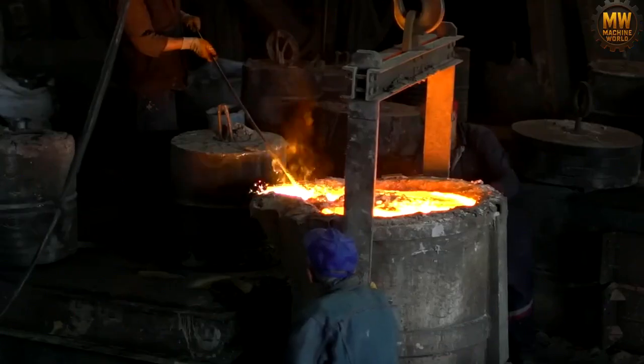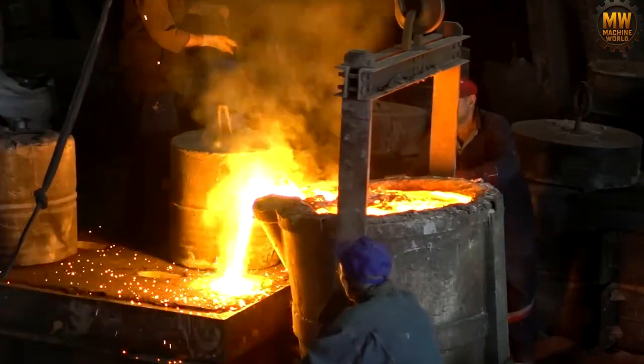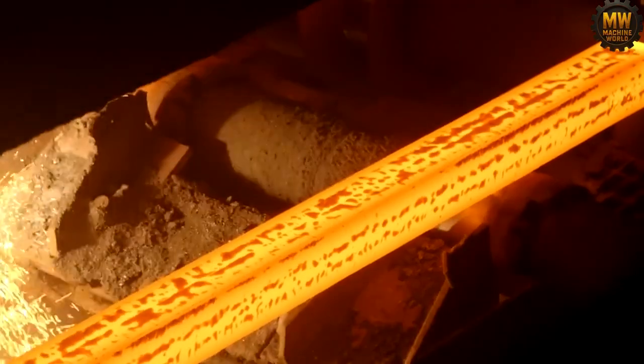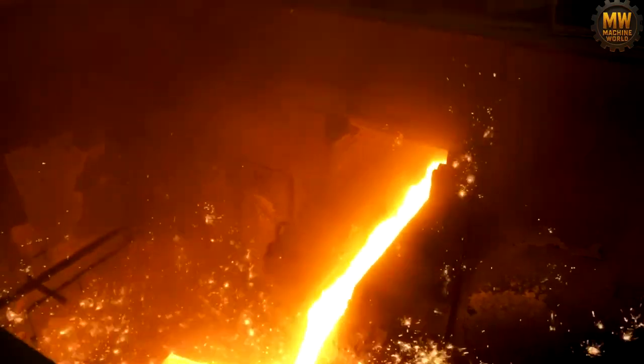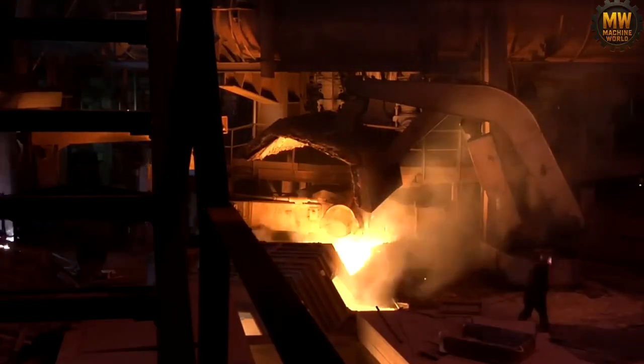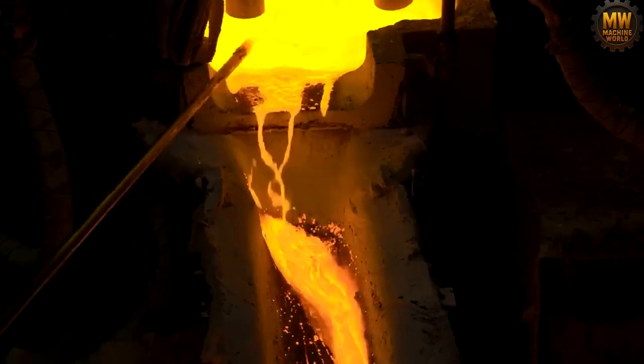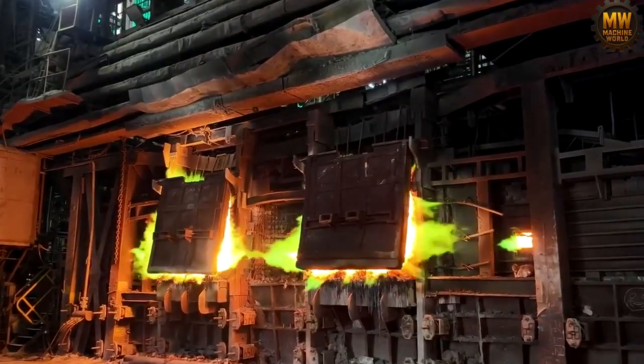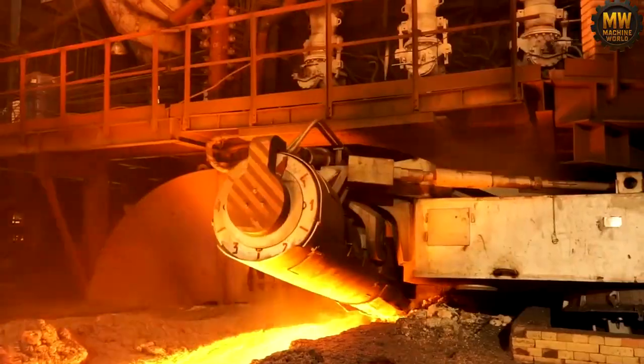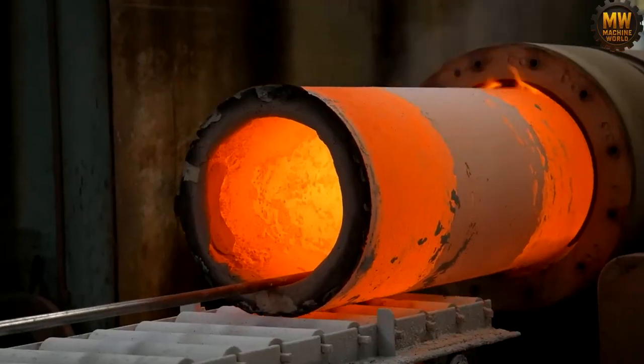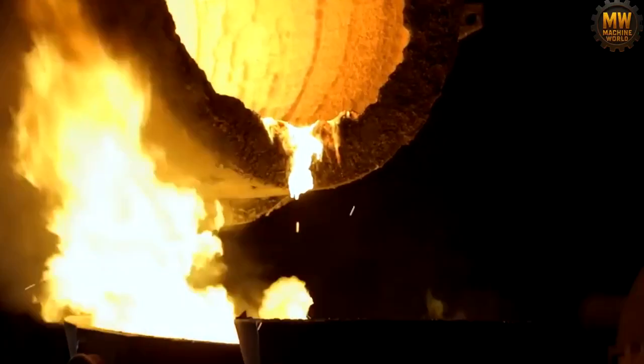The compounds trigger a rapid reaction, generating a thick layer of slag on the glowing surface. This floating crust acts as an aggressive chemical sponge. It physically extracts structural poisons like phosphorus and sulfur from the molten iron matrix. Once chemically perfected, the liquid steel drops into a continuous casting line, plunging rapidly through water-cooled copper molds.